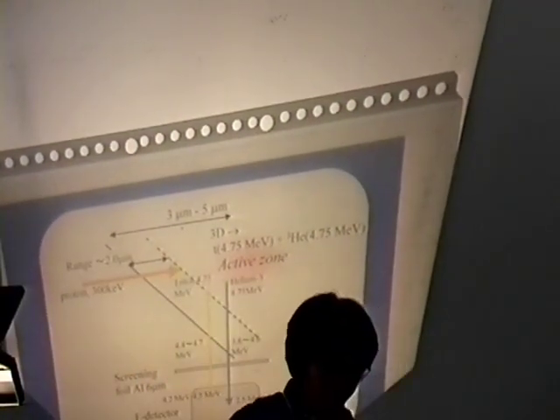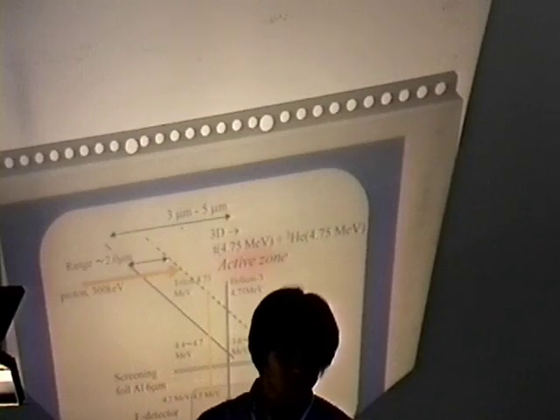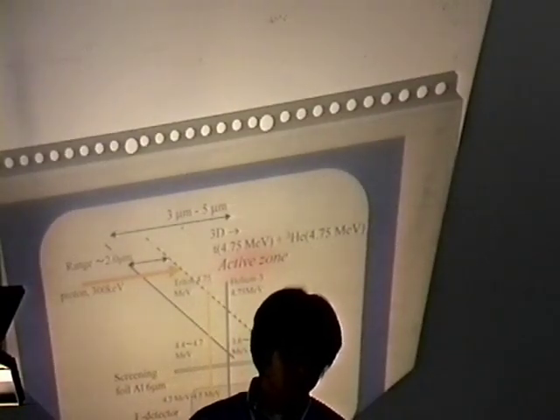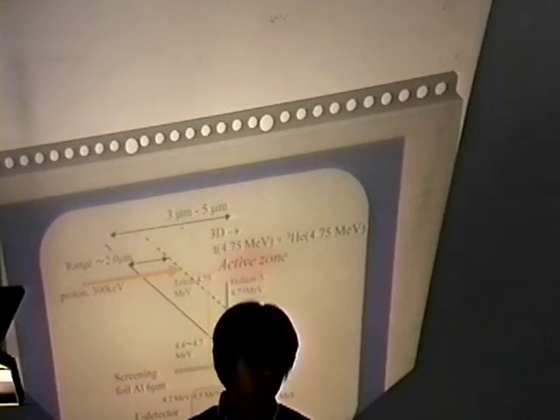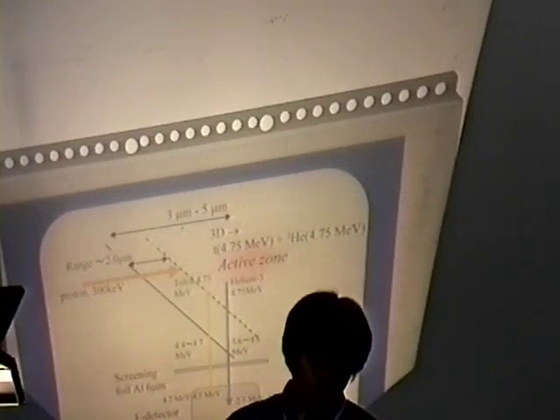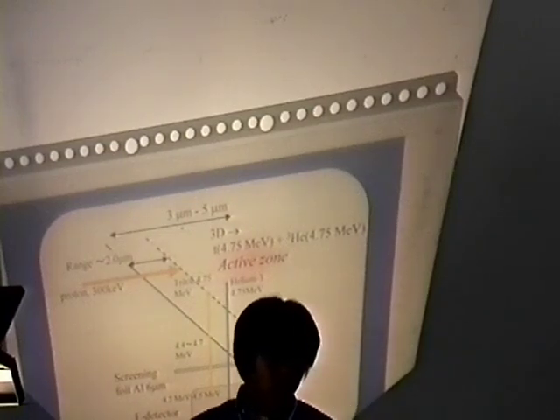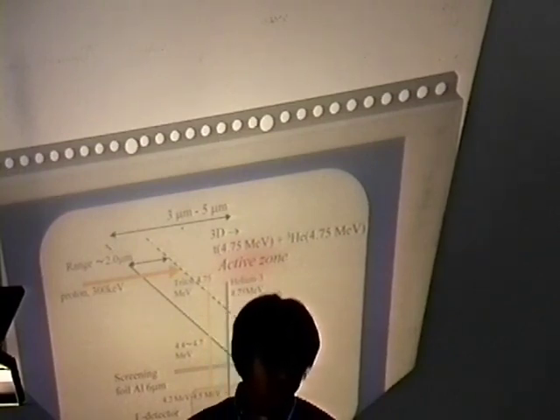And this explanation is consistent with the discussion of the results of the deuteron beam experiment. Therefore, the incident beam plays a role only in generating the condition in which the multibody D reactions are induced. In other words, multibody deuteron reactions are not direct beam-target interactions.